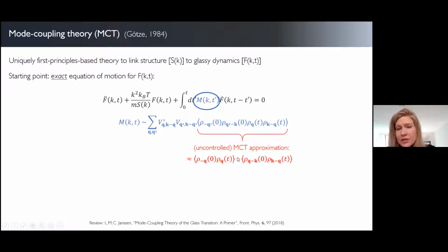But if you do this, you may recognize that these new 2-point correlation functions that you've produced here are in fact the very definition of our intermediate scattering function, for which we wanted to solve this equation in the first place, but just at different wave vectors q. So here one at q and at k minus q. And so this is mode coupling theory in a nutshell.